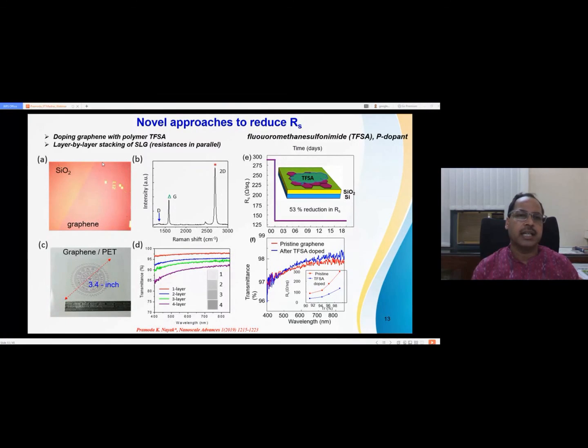So this is another technique. This is a simple technique and simple idea. What you do? You take the resistances in parallel. You have a graphene film. You can take 4-layer graphene. So what will happen? Due to the resistances in parallel, the net resistance will decrease. So you can have the high conductivity. So these are the two approaches we follow.